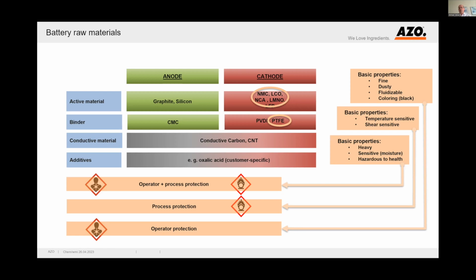And the most critical materials, as mentioned before, are these cathode active materials. So there we have the issue of operator and process protection, because this cathode active material is always very heavy. So we talk about a bulk density of 2 to 2.5. It's often sensitive against moisture, and at least all NMC-based or LCO-based materials are hazardous. Only LFP is not so critical. Yeah? So the operator protection is on a higher level here for these materials.